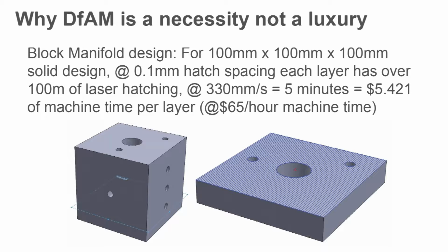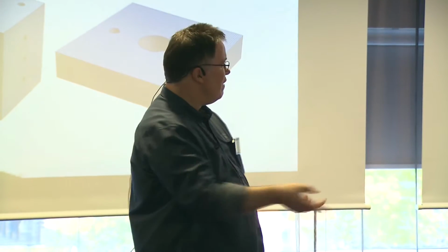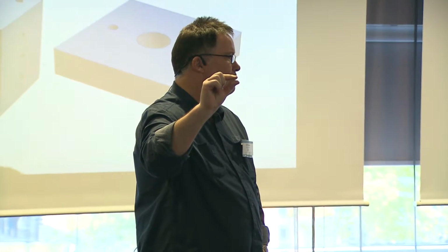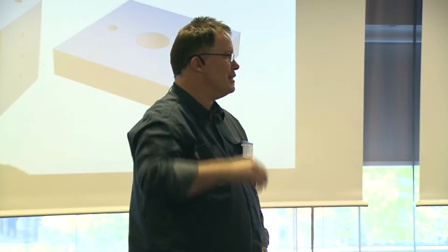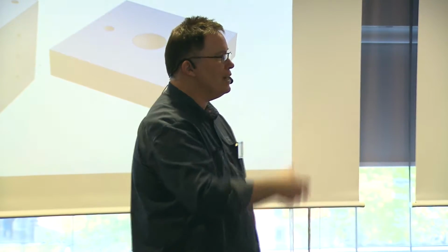That means each slice is going to take 5 minutes to actually produce. So 5 minutes, that's worth about $5 per slice. If your slices are 50 microns per slice, you've got 2,000 slices in it, you're suddenly talking $10,000 to produce a part. Now you start to care about, well, can I design this to minimize that time?